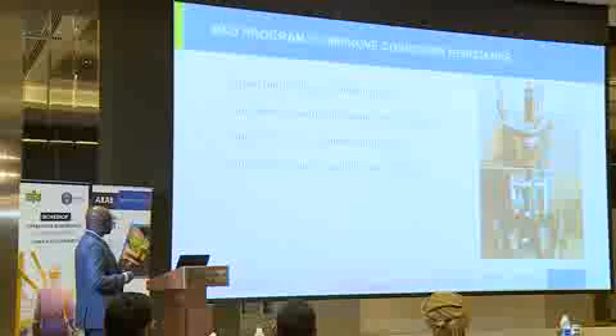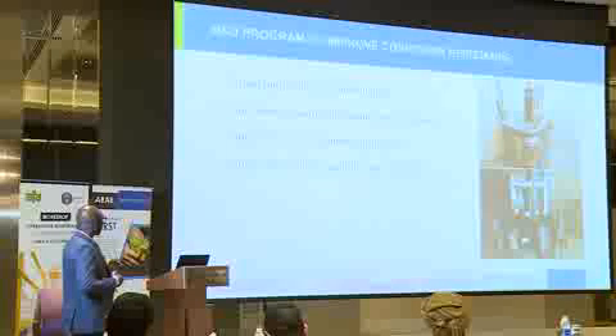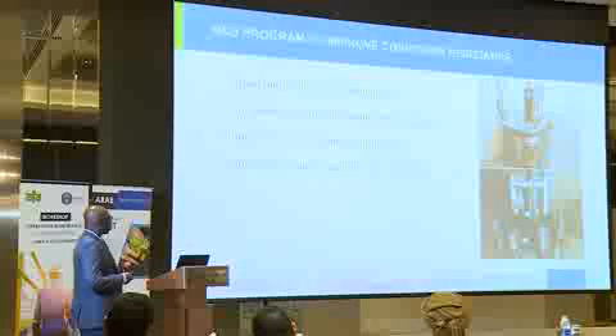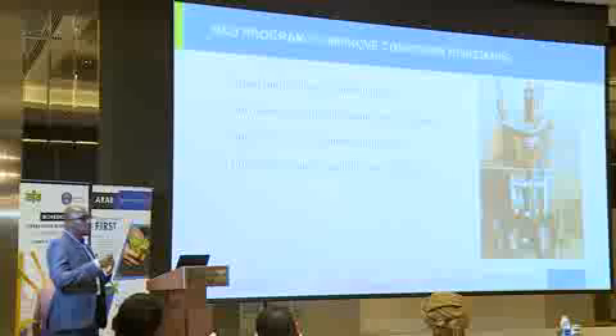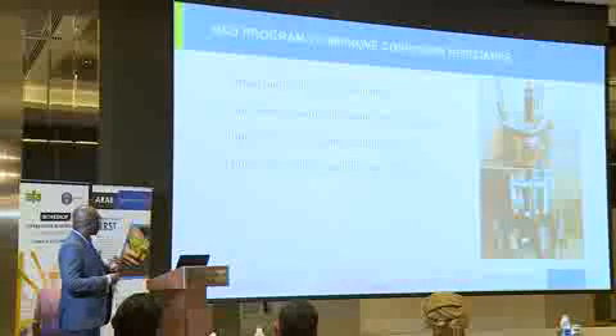We also wanted to make sure that the material that we come up with will have equal or better mechanical properties than the standard Safurex, and also that we will have a good structural stability and weldability. And this is because for duplex stainless steels, the more you try to improve the corrosion resistance, you run the risk of having issues with structural stability, especially when you weld.